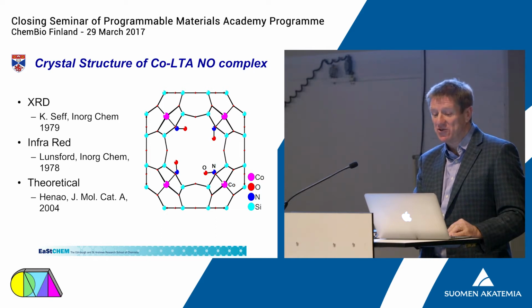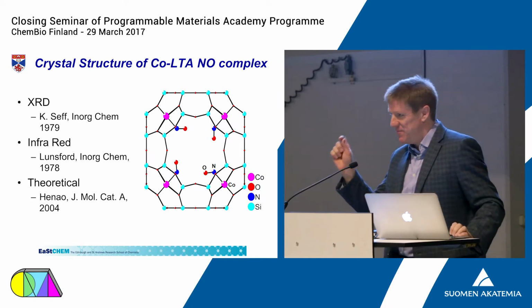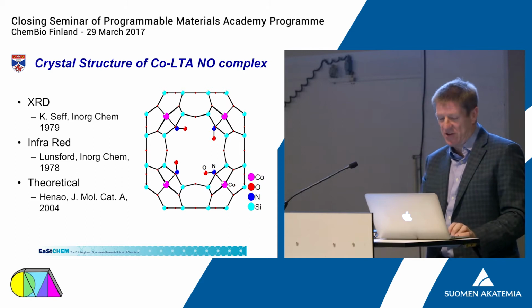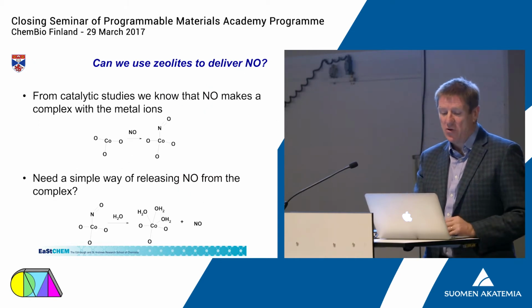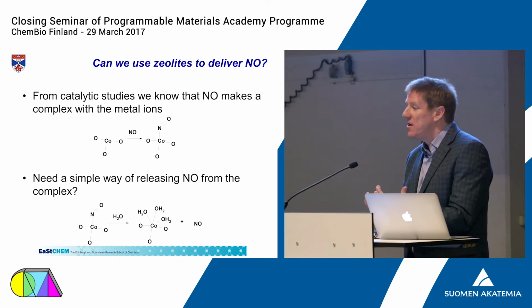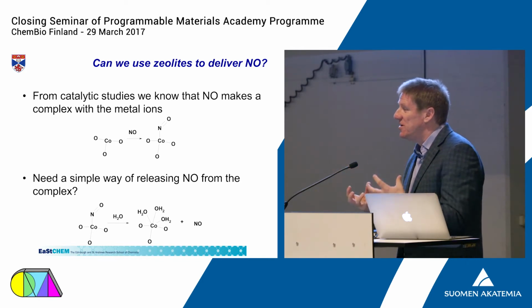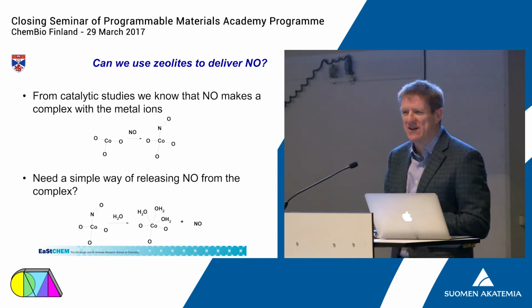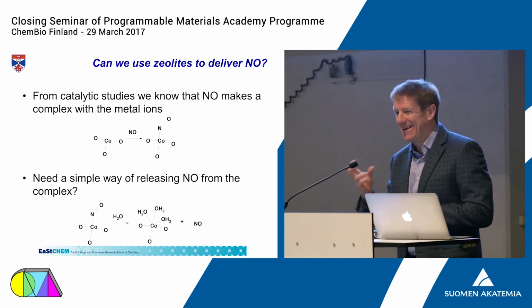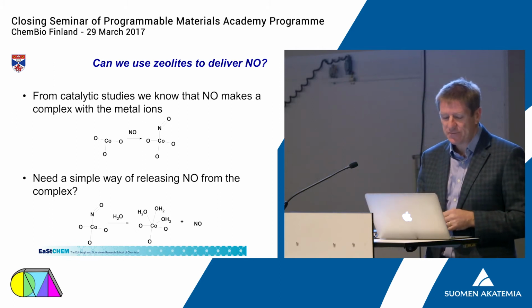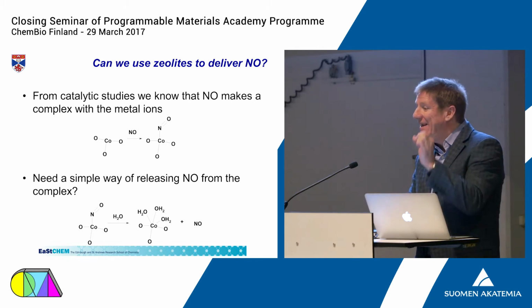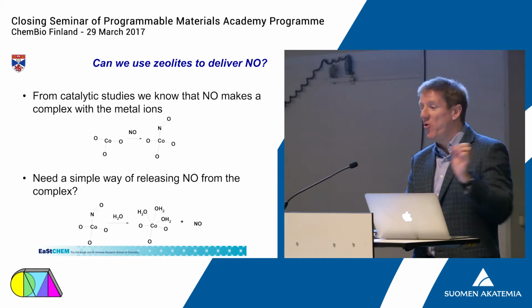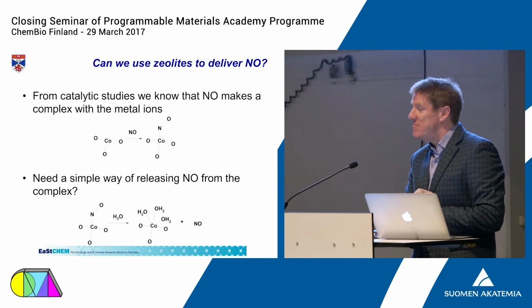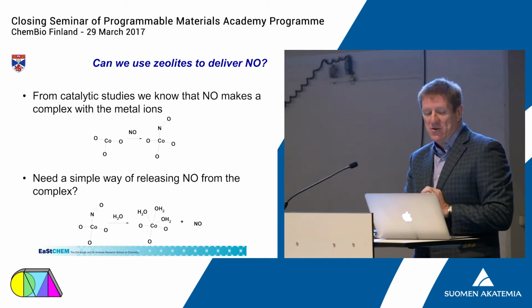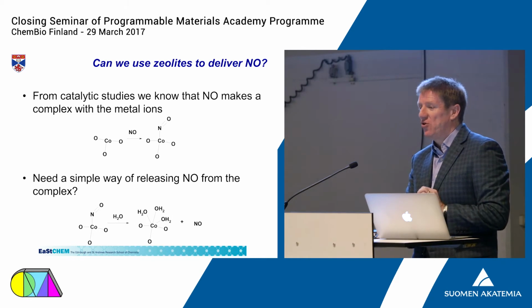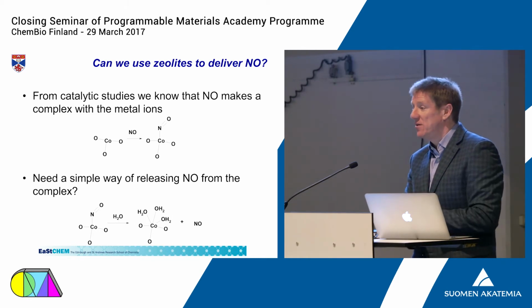This one's a structure of a cobalt, which we don't use in the medical applications because cobalt's not very nice, but we use other things like zinc. So we know that if we put nitric oxide into these materials, they attach to the metals really quite well. Nitric oxide, for the chemists amongst you, is not a bad ligand. So the actual key to the process is, if we put nitric oxide onto that metal site in these zeolites, we need to ensure that when we need it back again to do its job, we can get it back.